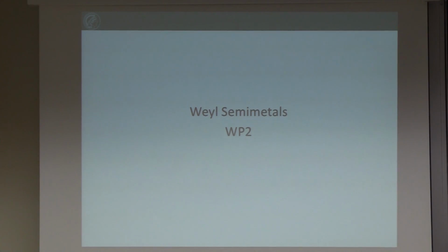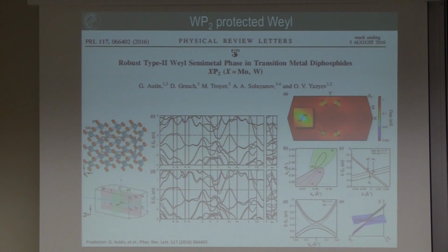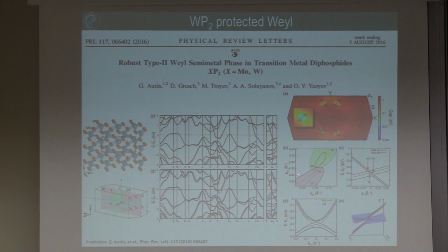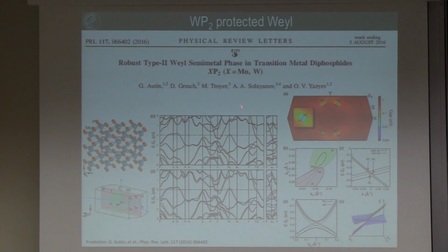So in this context, we were looking for other materials besides niobium phosphide, and one material which we liked especially was predicted by some people from the PSI. It's tungsten phosphide 2. It's a Weyl semimetal, and it's a protected Weyl semimetal. Why is it a protected Weyl semimetal?